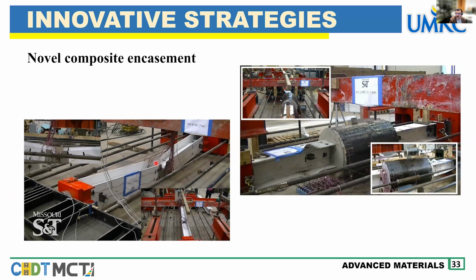As you can see, this is the column without the proposed novel composite encasement for the retrofit. And this is the column here with this severe corrosion level. We were able to transfer the local buckling, as you can see here, from the damaged section, which is now repaired, to the healthy section. And we achieved the goal of using the encasement as a repair method.